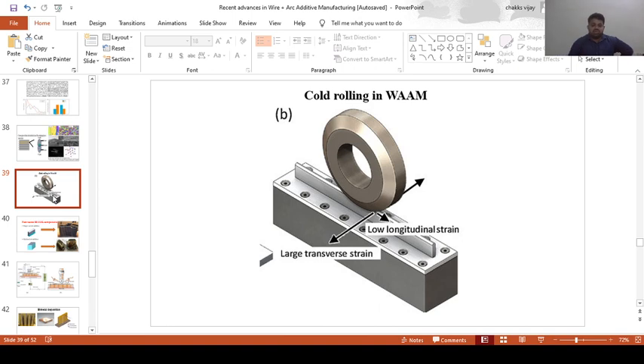Especially during cold rolling, the coarser grains get crushed and form a very fine grain structure. However, one of the most important things is that this roller dissipates the heat, especially from the deposited area. So faster heat dissipation is possible, and even coarser intermetallics can be broken into finer fragments, and grain refinement can also be achieved. But one of the most important things to consider is that excessive rolling load will lead to tearing of layers. So only optimal rolling load should be applied. That should be given more significance.